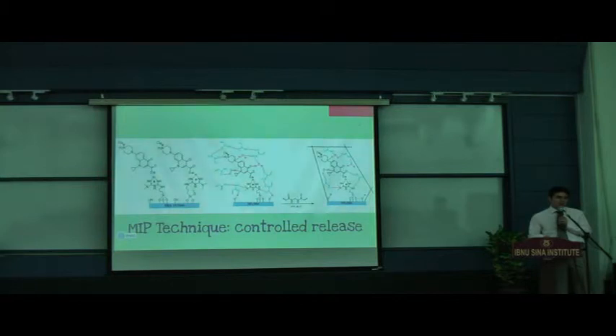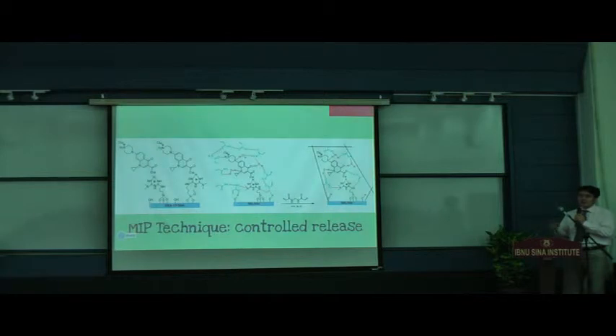So, the final application was bioapplication. I'm not going into details, but simply when you have metformin attached to the surface, as I mentioned earlier, it is an organosuperbase. If you take a medicine with acidic property, then you can simply see proton transfer between them. For example, this is ciprofloxacin. If you take ciprofloxacin, you'll immediately see this proton transfer here and electrostatic interaction between the anion of the medicine and protonated metformin at the surface.